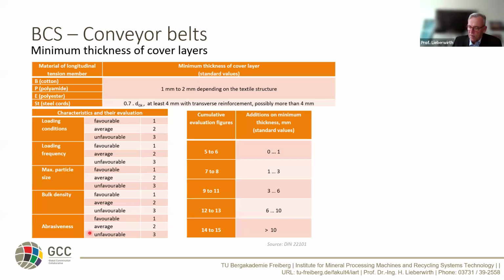So we had an overburden in the Claremont coal mine in Australia. In some corners of that mine, we had sticky material, so the chutes were blocked. Then we made nice sliding devices. We removed the sliding devices, and then the original material, which is a basalt and very sharp-edged, was breaking quite easily. It was much more competent than originally specified, but it was breaking nicely, with very sharp edges. And so when the chute was not guaranteeing the sliding anymore, it was really eating off the belt. It was chipping off rubber every time a larger block jumped onto the belt. So abrasiveness is an issue, sharp edges, very important.